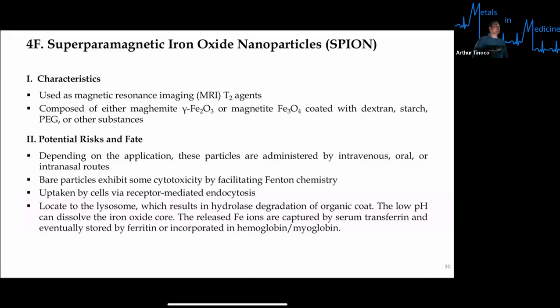So as you can imagine, there's going to be a risk associated with something that contains iron and that can potentially release iron. So depending on the application, these particles are administered by intravenous, oral, or intranasal routes. Bare particles exhibit some cytotoxicity by facilitating Fenton chemistry because of the iron that composes them. They are taken up by cells via receptor-mediated endocytosis. They locate to the lysosome, which results in hydrolase degradation of the organic coat, and the low pH can dissolve the iron oxide core. The released iron ions are captured by serum transferrin and eventually can be stored by ferritin or incorporated into hemoglobin and myoglobin. So that's the desirable fate of the iron, that the iron does not lead to just a release that's unregulated, but that it actually can be captured and properly stored.